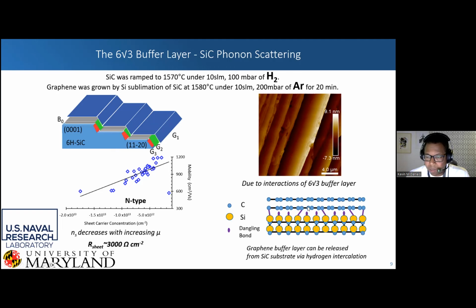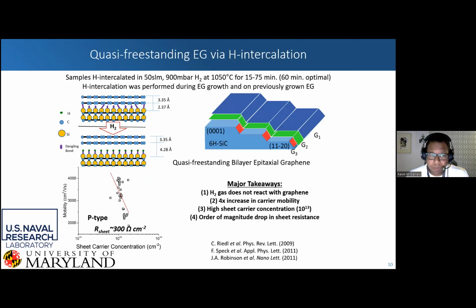So the question is, okay, can we passivate these silicon dangling bonds in order to release this carbon layer here, and can we remove this electron-phonon coupling between the two materials? And the answer is yes, we can. By introducing close to atmosphere hydrogen at around 1050 C, varying the time, 60 minutes generally optimal, you can passivate these silicon dangling bonds. You can release this layer, forming these really nice graphene layers, and the mobility goes up by roughly 4 times.